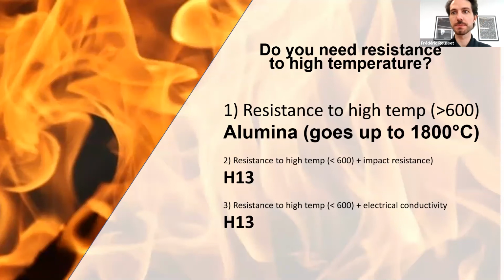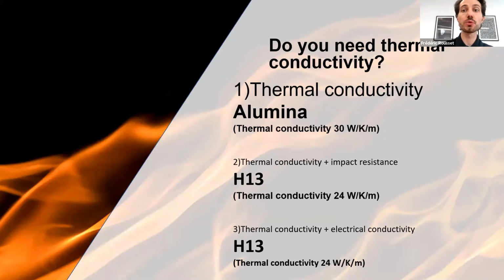After that, I'm going to present the different questions that we have to select the material that you need. If you need high temperature resistance, you can use the alumina that goes up to 1800 degrees. If you need to go lower, you can use the H13 at lower than 600 degrees, if you need an additional property like impact resistance or electrical conductivity. For thermal conductivity, you also have to use the alumina. This is the best one, the ceramic one. And of course, if you need other properties like impact resistance or electrical conductivity, you can use the tool steel, which is very good as well.